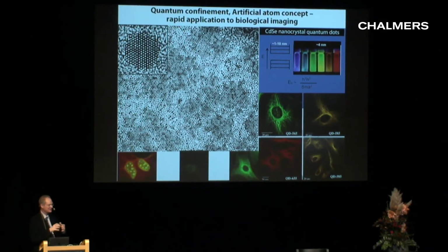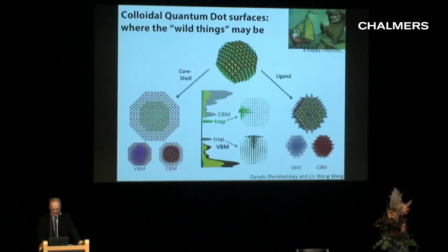And that's what happens inside one of these tiny crystals, is if we push the electron and the hole into a tiny, tiny volume, a smaller one than they would like to occupy normally, they start to move very, very fast, and their band gap increases, and the color of light that they absorb and they emit changes from what would normally be there. And that's called quantum confinement, or the quantum size effect. And it's related in its essence to going from a continuous material to a tiny atomic or molecular one. And it means that we can tune the energy levels as a function of the size of the crystal. We're going to use that. We're going to make many different colors that way.